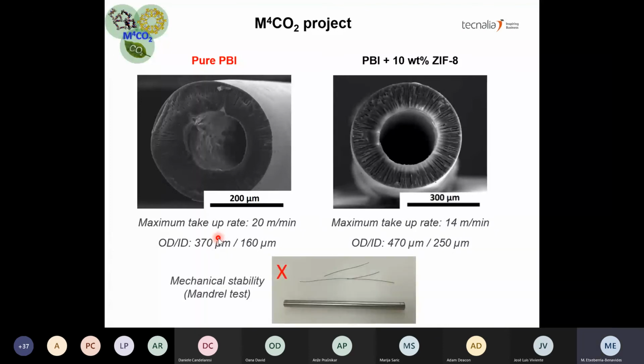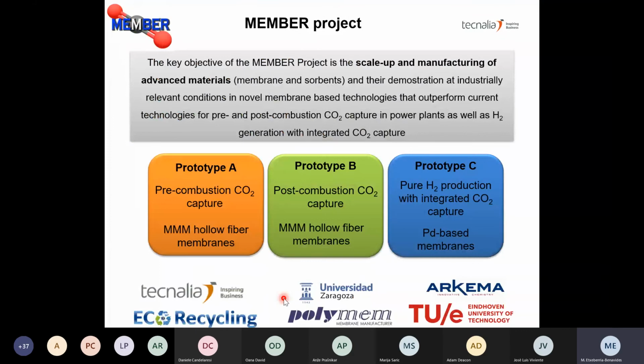On the other hand, the mechanical stability of this fiber was not quite good. We subject the fiber to a mandrel test. A mandrel test shows the ability of a fiber to wind and unwind in a 1/4 inch tubing without breaking. So during this test, the fiber was breaking, and these fibers do not pass this test. So in the following slides, I will talk about the MEMBER project.